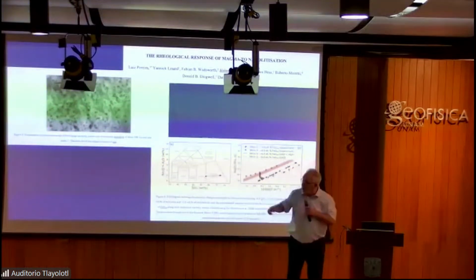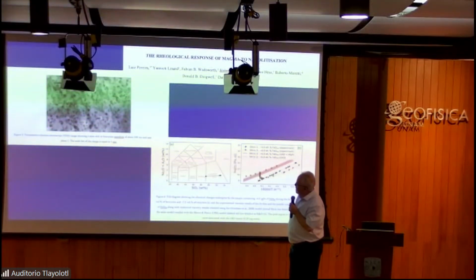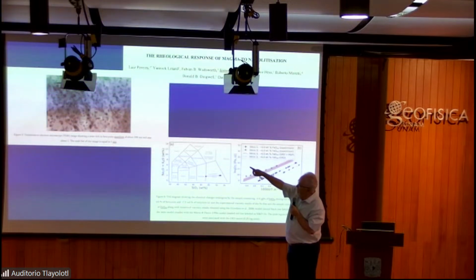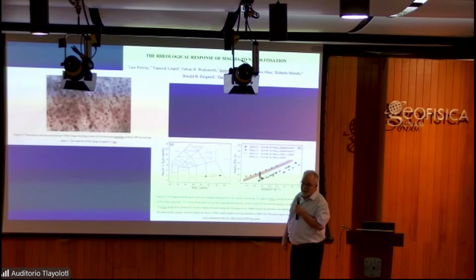And what you see there is a TEM shot. And this is 1 micron as the scale bar. So you see you're down in the nanolite range. We're way below 1 micron. And you see it's quite a volume fraction which is turning up there. This could have a physical effect on the viscosity. So imagine a system in eruption.